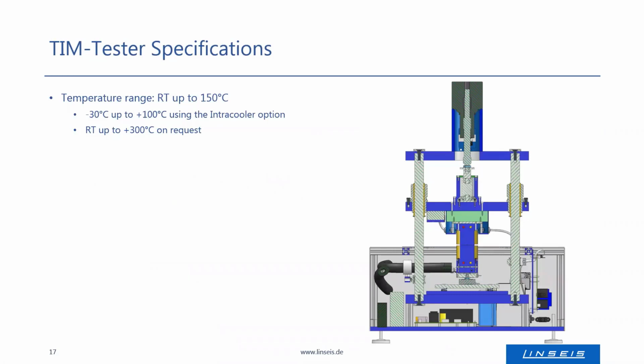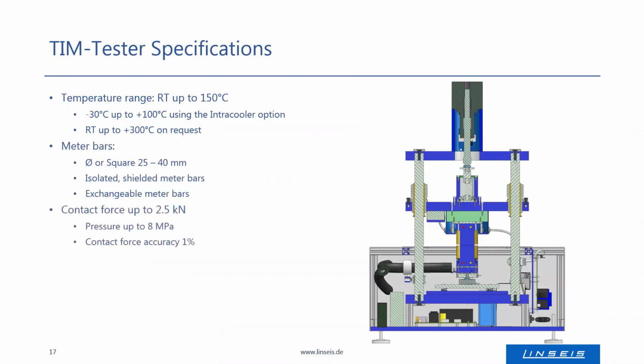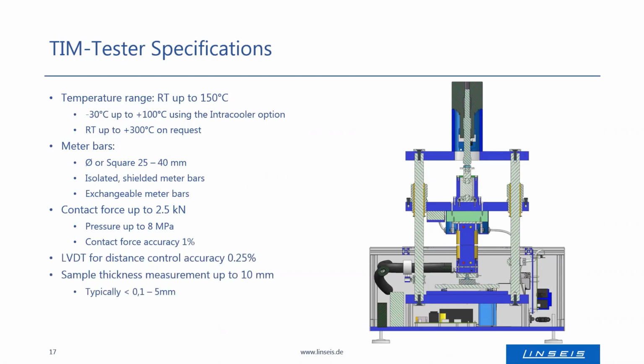Now we come to the TIM tester specifications in more detail. The system can be in a standard configuration used for measurement in the temperature range from room temperature up to 150 centigrade. With a different intercooler option, one can extend this range from minus 30 Celsius to 100. Or with another modification, one can measure from room temperature up to 300 centigrade.